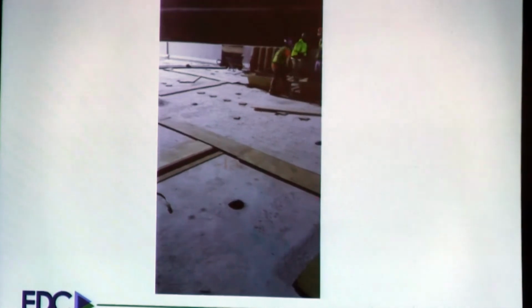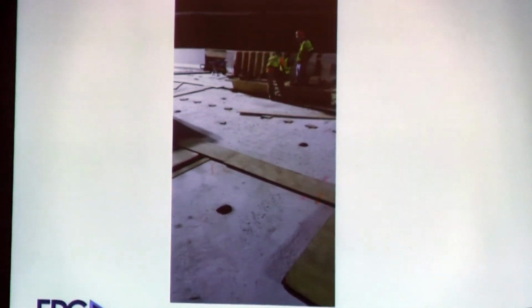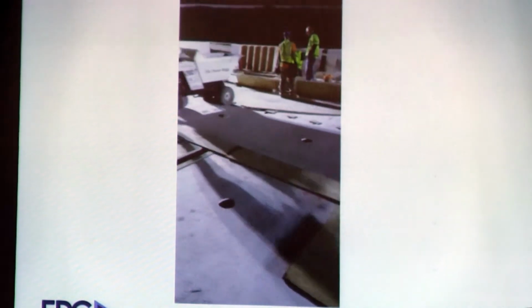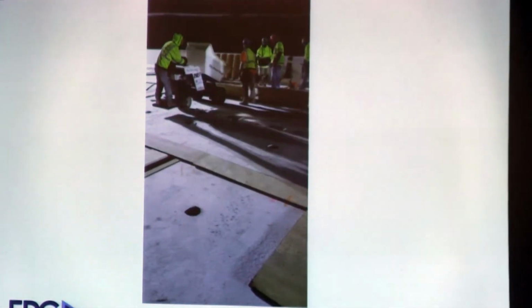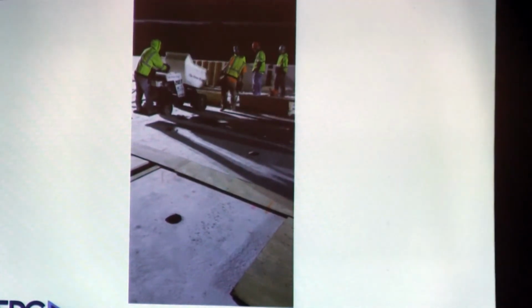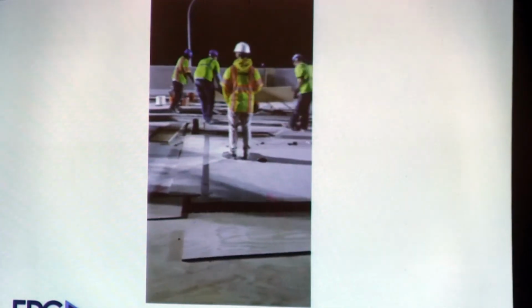And in the video, you'll see they bring in the little buggy that's carrying the UHPC. He'll come in, he's going to dump it into the trough. The troughs are set up over the joints. They actually filled up a lot of the joints without the top form. And then when they get near the top, they would put the top forms on. The top forms are set about a 1/2 inch high, and then we just come back and we'll grind the difference off.